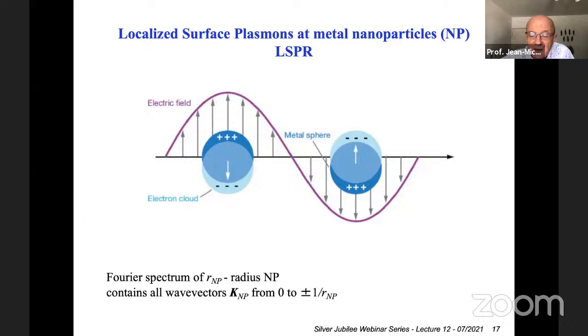What happens is that the electrons of the metallic nanoparticle are excited exactly by the light, following the light. The dipole of the light is oscillating, and the electrons react to this, so they go exactly, of course, in the opposite way. When the polarization of the light is positive, you get a negative charging, and when the polarization is negative, you get a positive charging of your electron cloud, which means that the electron cloud is moving around the nanoparticle. Owing also to the small size of the nanoparticle, this creates an enhancement of the light close to the nanoparticle, which can be calculated by different methods.